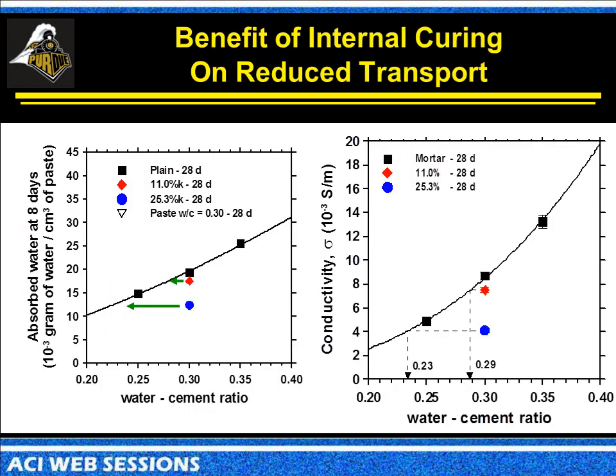As I mentioned before, in addition to just the effect on hydration of getting increased strength, we have the effect of getting reduced transport properties in these systems with internal curing. So this is just looking at a plain system, and the whole idea here is as we change our water to cement ratio on both x-axes, we can either measure the amount of water that's absorbed, or we can measure the electrical conductivity, which is very similar to an RCPT number. Plain systems are the dark dots here.